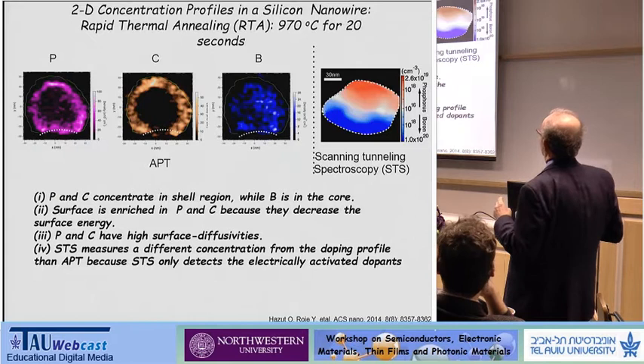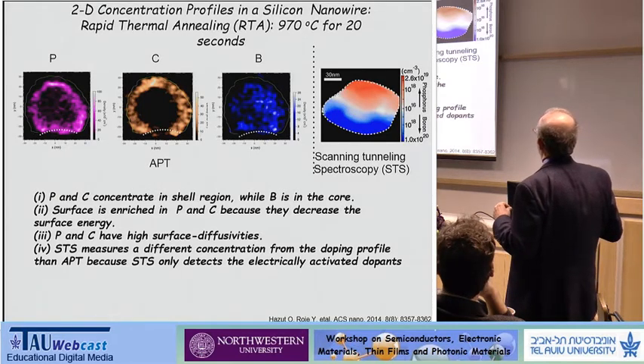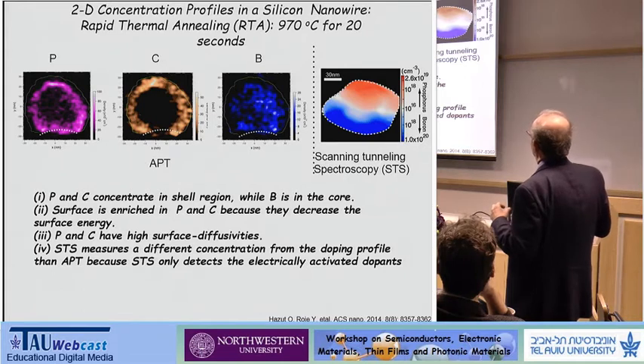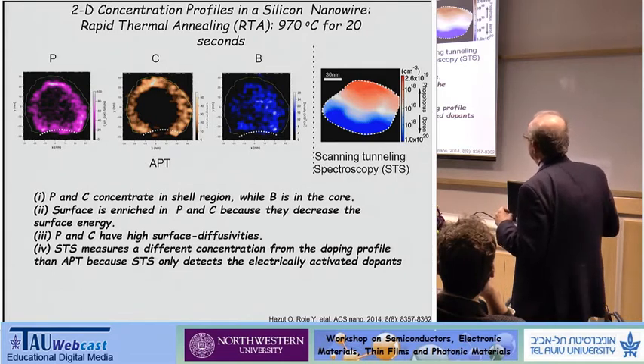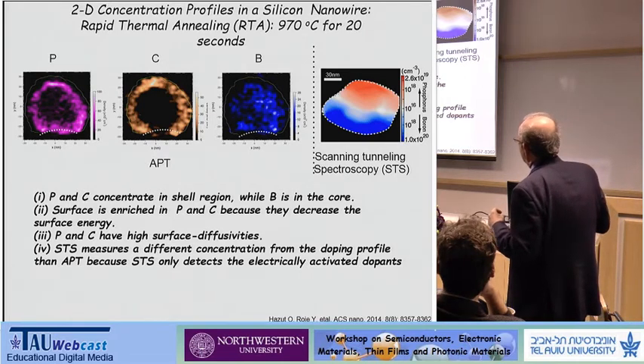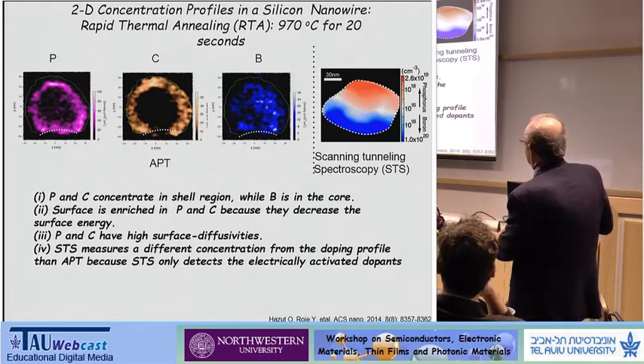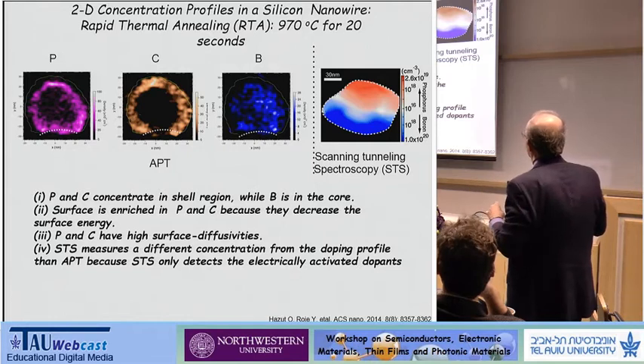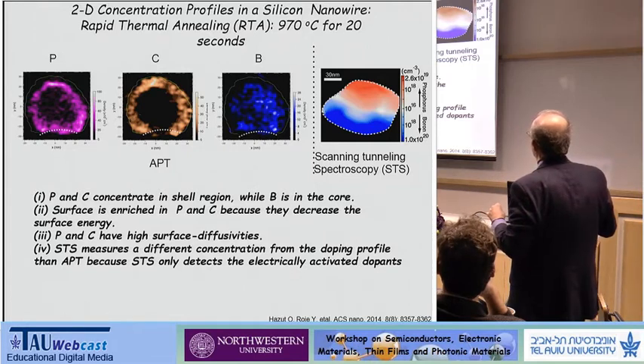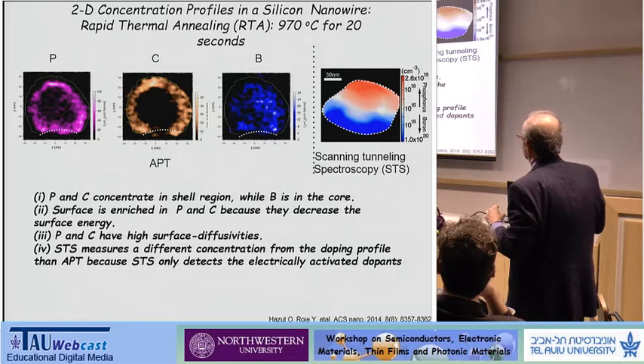Okay, here are the results. So all the experimental results I'll show you are a result of rapid thermal annealing at 970 degrees C for 20 seconds. And what I'm going to show you are concentration profiles in the silicon nanowire. So here's the distribution of phosphorus, and here's the distribution of carbon, which comes from the organic precursor, and here's the distribution of boron, which is more or less uniform.